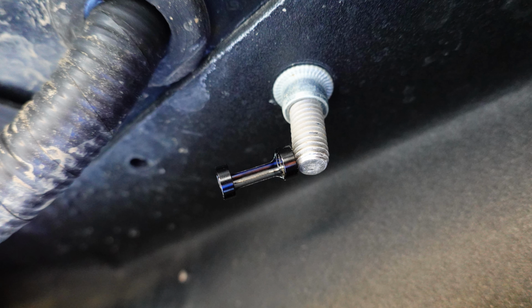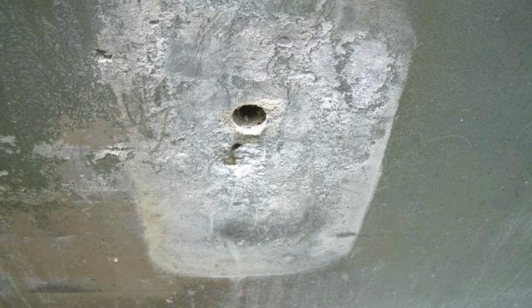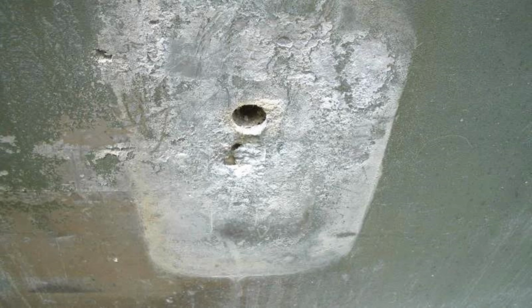There's also no way you can fasten down a bolt with threads through two metals, even if they are coated, without abrading the paint coat in the hole with the thread of the screw or the bolt. The smaller the contact surface between the dissimilar metals, the greater the galvanic corrosion. Here is an example of what I'm afraid of. This is from an aluminum boat. This looks like the bottom of a trailer with an aluminum plate on the steel chassis. Here a piece of steel was attached to the aluminum plate with a steel bolt, and you can see how galvanic corrosion occurred around the bolt opening and on the contact surface between the aluminum and the steel.